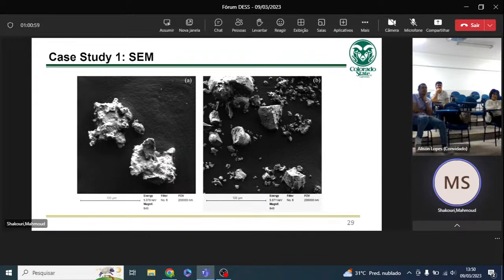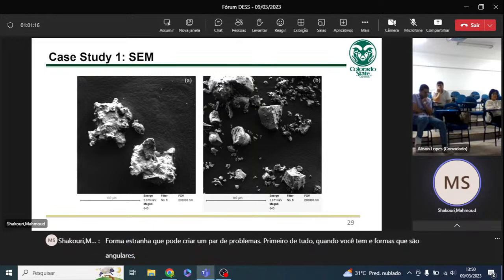In terms of particle size morphology, they are not really rounded shapes. They have these weird shapes that can create a couple of problems. First of all, when you have shapes that are angular, it increases the water demand for your mix. So what it does to your concrete is it makes your concrete less workable. So when you add this into your concrete, it becomes stiffer, and that's the issue for all types of residues.